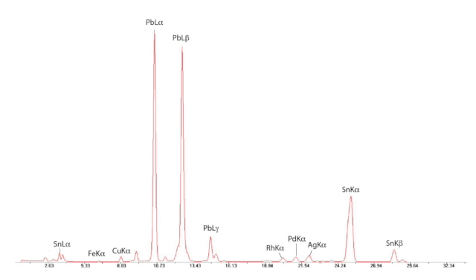Archaeometallurgists use a variety of methods to determine the alloys that ancient metal workers used. One of these is X-ray fluorescence, which allows us to identify many of the elements in a material by their distinctive X-ray energies. The X-ray spectrum you see here, for example, has high peaks at energies associated with lead and tin, and only much lower peaks associated with elements such as copper, iron, and silver. This is consistent with an alloy called pewter.